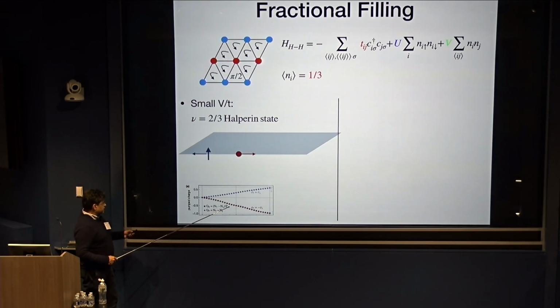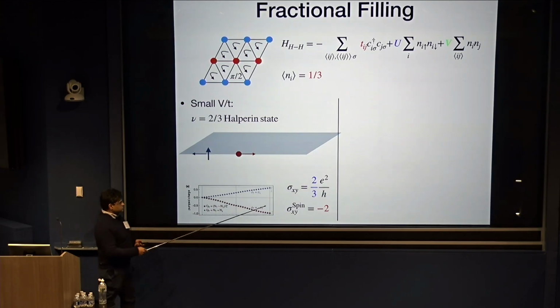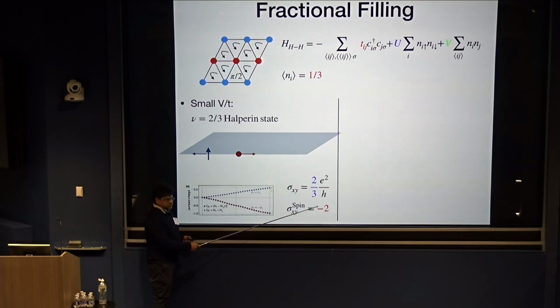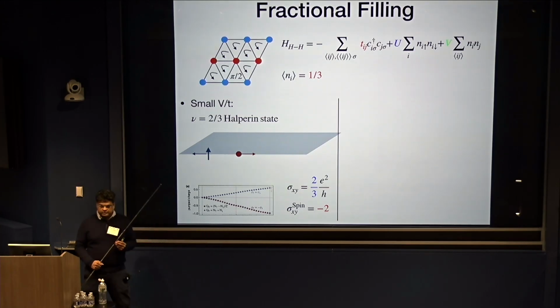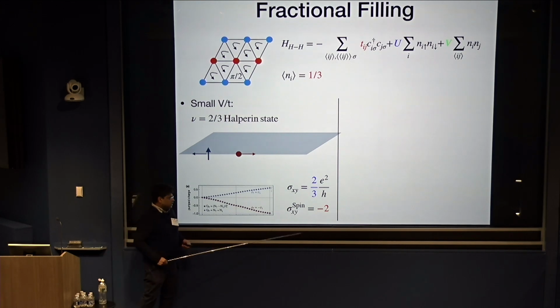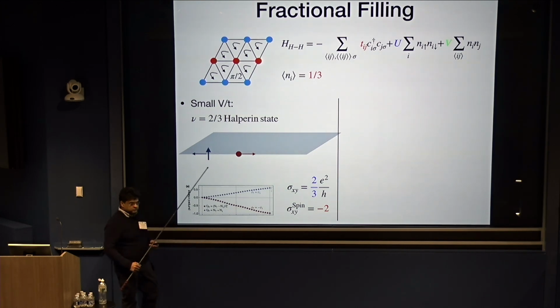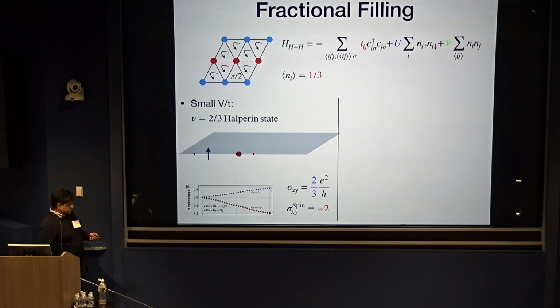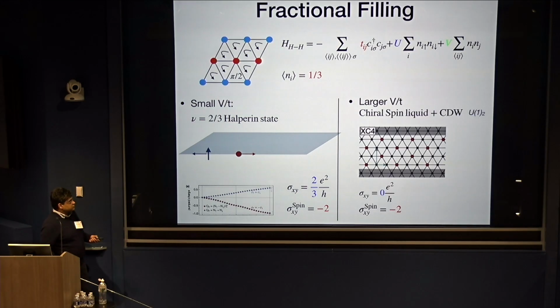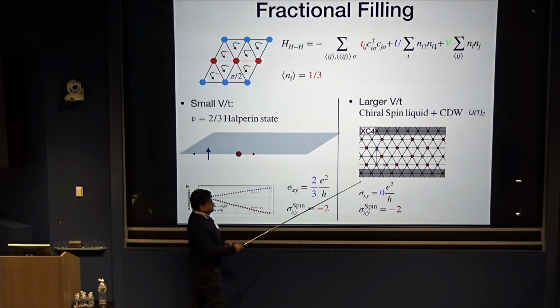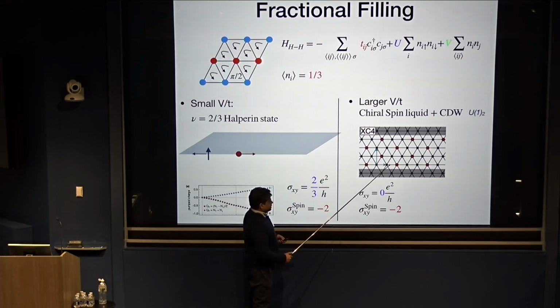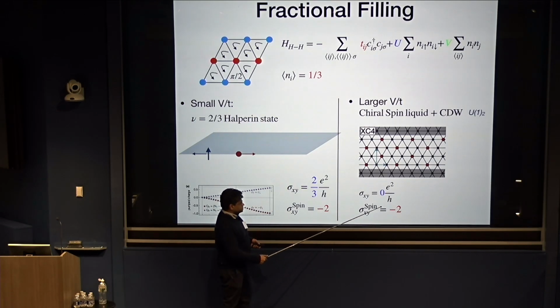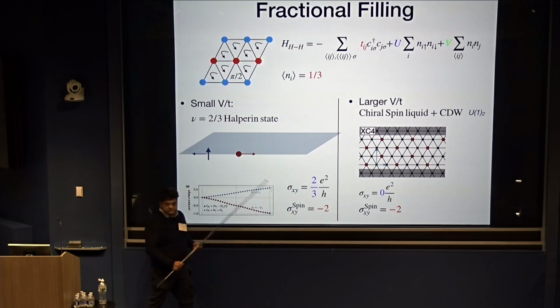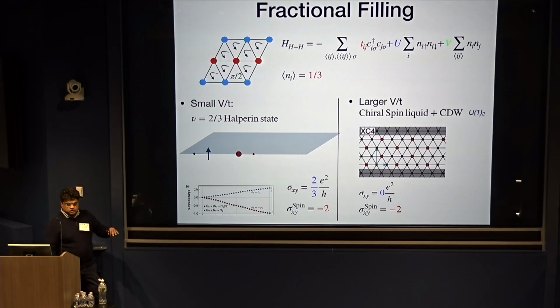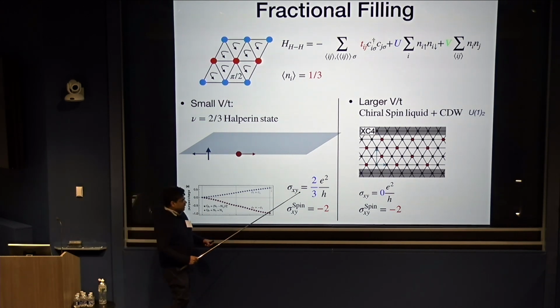And what you can see is the charge response is two-thirds of the quantum of conductance, and the spin response is -2. The spin response in a model with SU(2) symmetry has to be multiples of 2, whether it's fractionalized or not. So this spin response is -2. Okay, so this is the Halperin state for this two-thirds. And then if you crank up the interactions V, you end up getting this CDW. Numerically, it's found that you get the CDW, which has no electrical Hall response, but it has the same spin response as the other phase. So it's very much like our previous example. Spin response goes right through, but the charge response changes, and you end up getting this insulator.